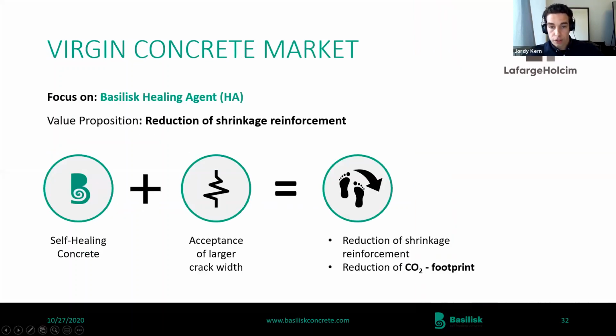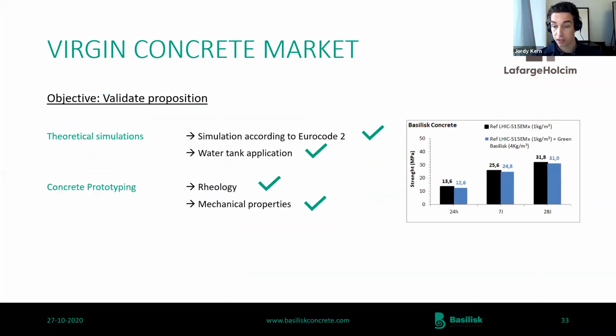For the virgin concrete application, we looked at this with LafargeHolcim. We focused on our Basilisk healing agent additive, and especially on our value proposition for shrinkage rebar reduction for watertight applications. Our claim is that it is possible to accept bigger crack widths due to the self-healing properties. And this will result in a reduction of shrinkage reinforcement and therefore a lower CO2 footprint of the concrete element. We validated this with theoretical simulations on a water tank case, and the results show that it's indeed possible to significantly reduce shrinkage reinforcement. Furthermore, we have looked at the influence on rheology and mechanical properties of the concrete mix when adding our product, and the results show there's no substantial difference compared to the control mix.